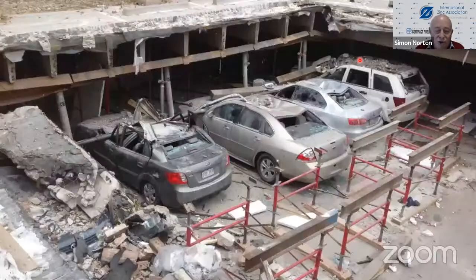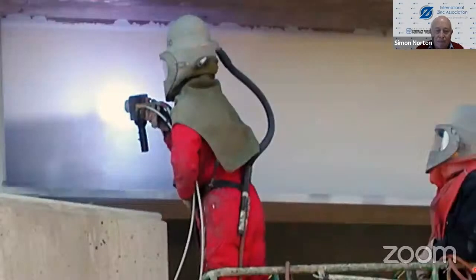You need to make sure you use zinc to protect against corrosion. It provides a powerful protective mechanism, and you won't end up with something like this. As you can see, there's a fair amount of corrosion there, and you can see the rebar inside this concrete looks rather thin. But if that had been galvanized, it's unlikely this event would have taken place. You can also carry out zinc thermal spray to protect your reinforcing steel or other steel structures. And this is another example of an operator doing such a job.